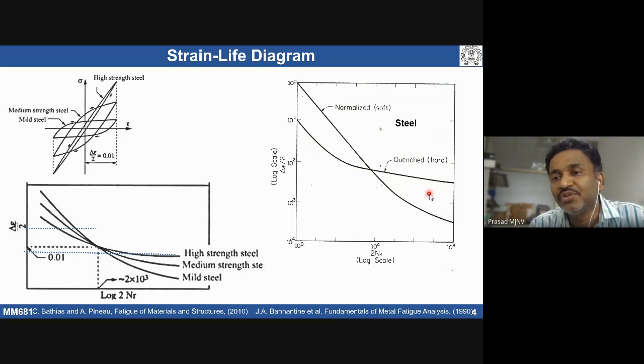Even if both materials are in elastic deformation, I always say most of the volume will be under elastic deformation, but something also undergoes plastic deformation locally. So for the crack to initiate, we need to apply high strain or high stress in the case of quench hardened steels as compared to normalized steel. Is it clear? At least this will be clear for all of you.